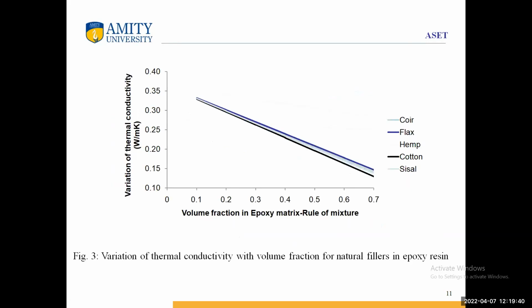In the third graph, sir, I am plotting the thermal conductivity, how the thermal conductivity behaves with the volume fraction changes in the epoxy resin with different percentages of filler. It is observed that as we increase the volume fraction of the filler in the matrix, the conductivity of the material decreases. It is highest at 10% filler, and lowest at 70% filler. For cotton or any of the materials, the trend is downward. If you increase the volume fraction, your conductivity decreases. This variation is observed by the rule of mixture, sir.